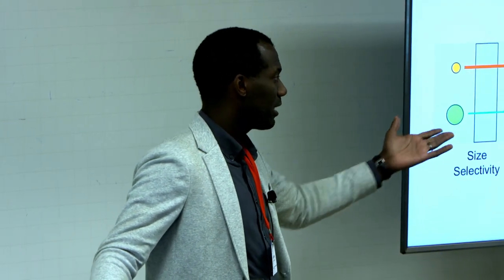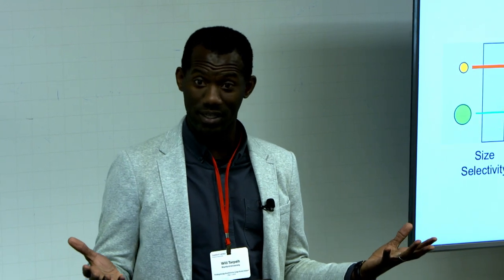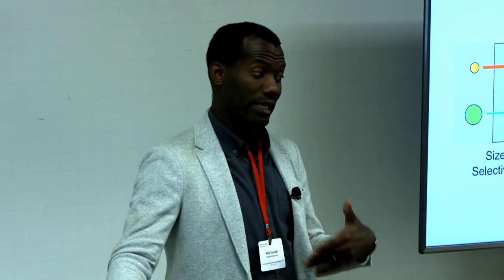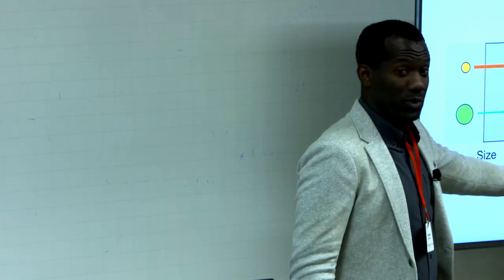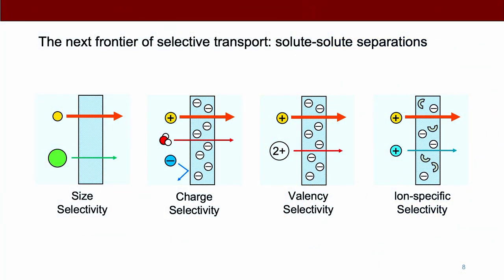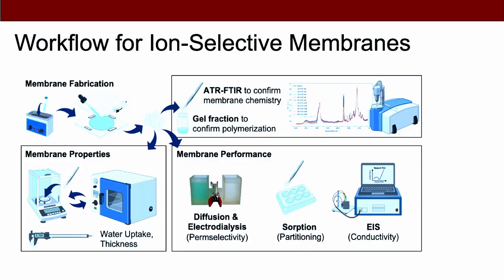So when we think about something like reverse osmosis, we're using size as the way to discriminate between water and ions, for example. People have also used charge, right? Nafion membranes do this very well. And recently, there are valency selective membranes. You can separate something like chloride from sulfate, potentially, by having different layers here, or also based on size, basically. But what we're after is adding ion-specific selectivity. So in short, adding chemistry to these membranes to really distinguish between lithium and sodium, for example. Again, really challenging, not something we're able to do yet, but we're starting to make progress.